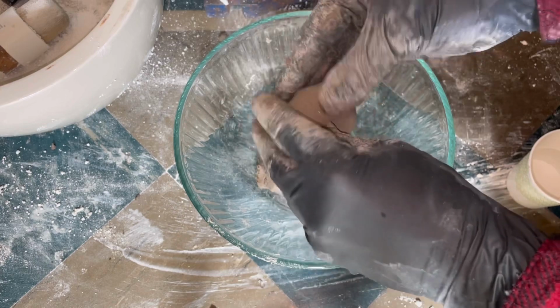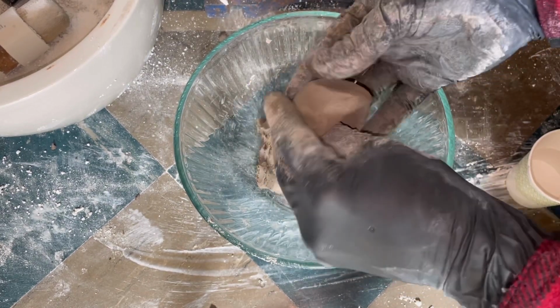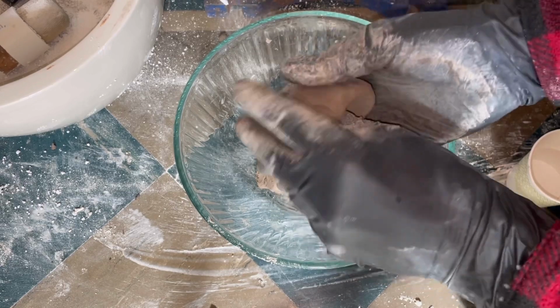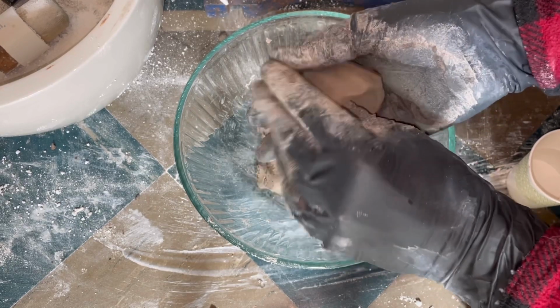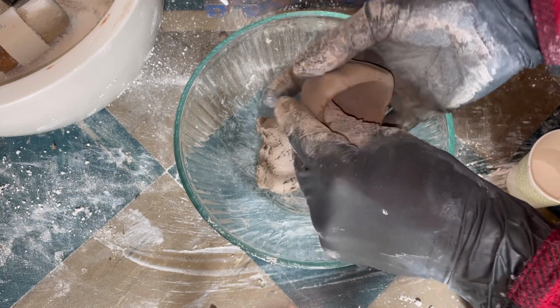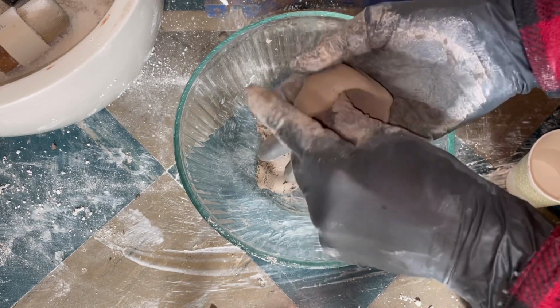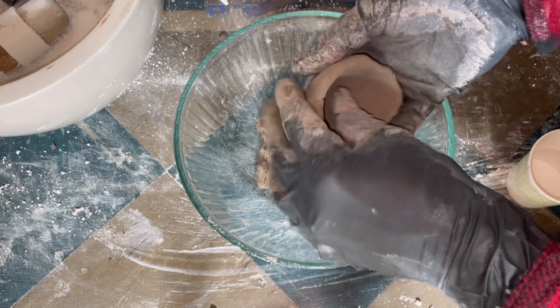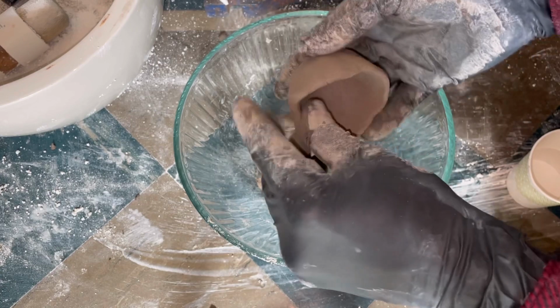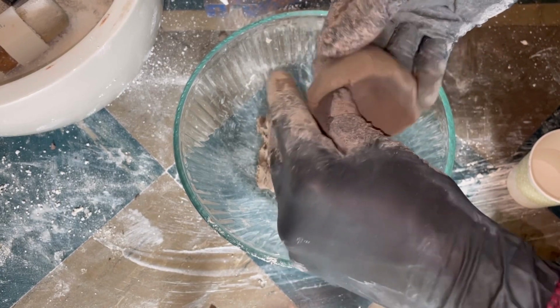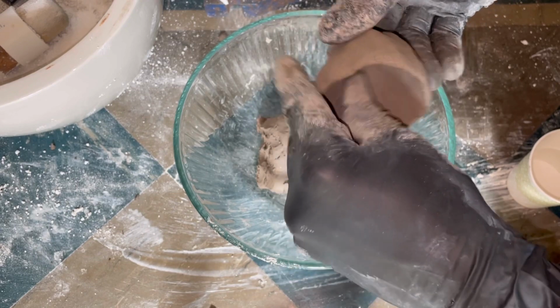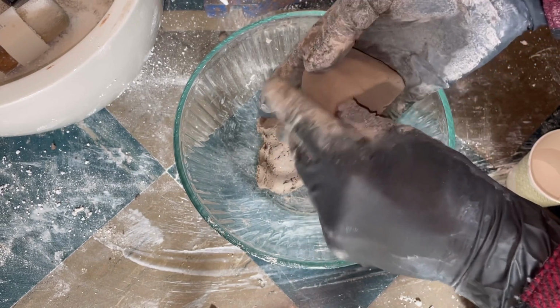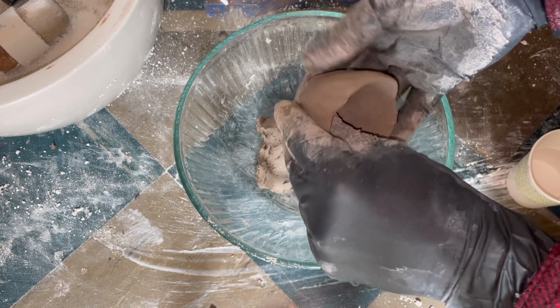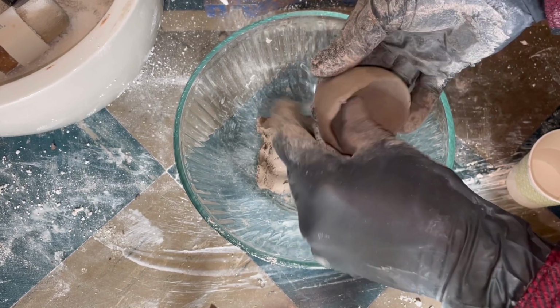And as for the actual crucibles, I've been doing just like a pinch pot, essentially. You probably could also use a potter's wheel for this. In fact, I think I'm going to buy a potter's wheel just so I can produce crucibles that are more uniform. You want to kind of have the bottom thicker than the top. Up here at the top, it doesn't really matter. That can go pretty thin because it's just to keep the material from overflowing. Down at the bottom, it's got to resist being dissolved by the flux. So it's got to be thicker because that's where it's going to be encountering the flux for the longest.